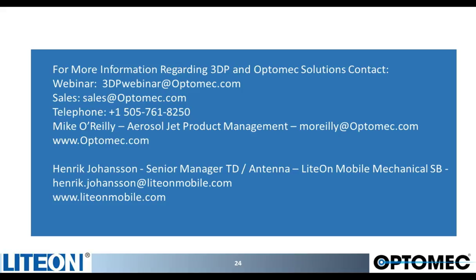At least from our side, Henrik, you can talk specifically about the antennas, but I can tell you that the vast majority of our customers are using standard drying ovens. When we do print materials such as copper, sometimes you need an oven that you can put a forming gas in so that you don't get oxidation of the copper. We also have customers that use lasers to actually sinter the material onto the substrate itself. We have people that use photonic curing, and we have people that will use UV curing depending upon the materials. So there's a wide variety of solutions that are available for curing the material. In the case of LiteOn, Henrik, why don't you answer that question? What do you use?